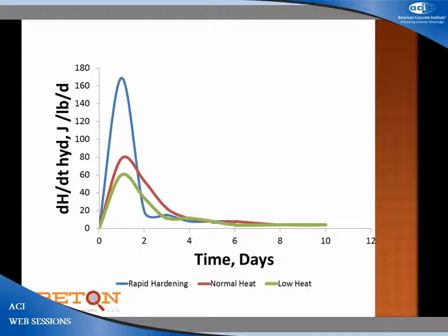Well, they all go into diffusion control about the same time. All three of them do, in fact, because the difference in these cements is just the grind, how finely it's ground. The slopes of these lines are different, because the slopes of the lines are the rate of reaction. You take the data from